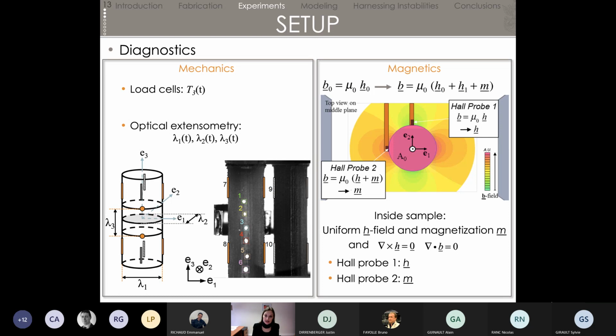The second equation tells you that you have continuity of the normal component of B. So if you put your Hall probe right at the interface on the left, Hall probe 2, you will measure the full B in the sample. And since we've identified H1 and then we know H, that gives us access to M. It's interesting to have those quantities, because the curves called MH curves tell you about how your sample is magnetizing. So that's all for what we measure. I'm going to show you now the results.